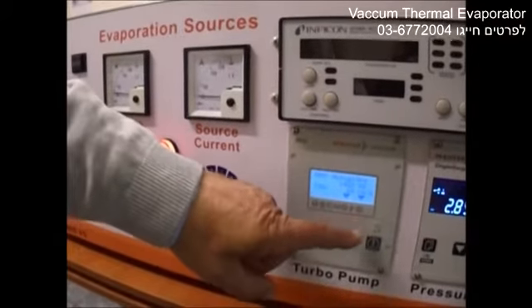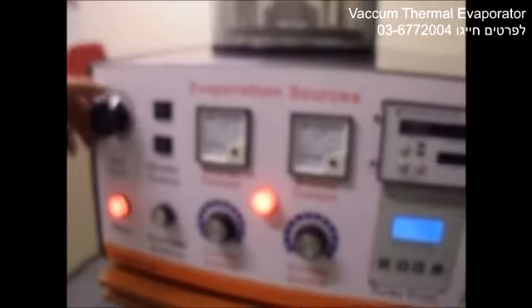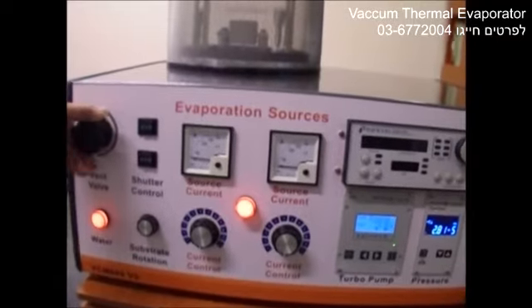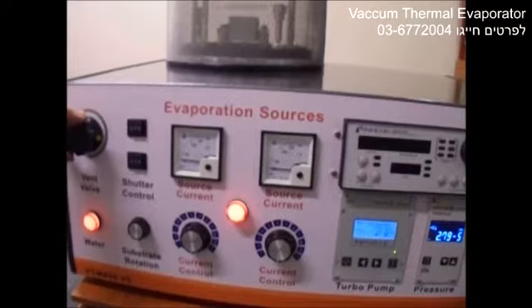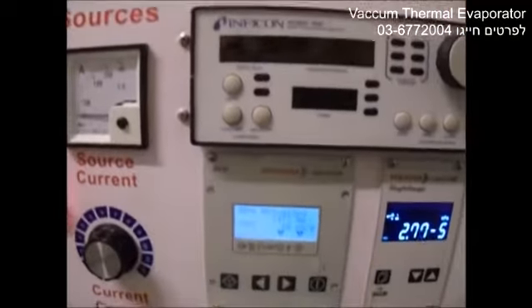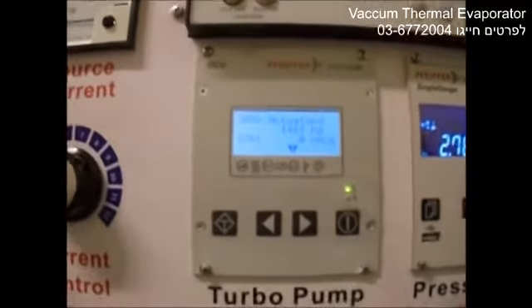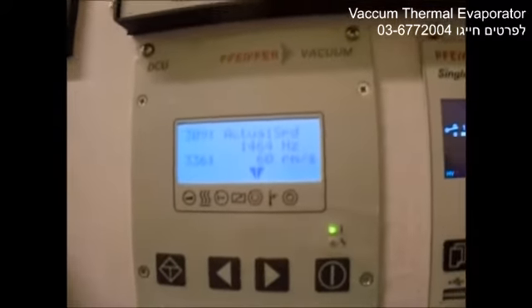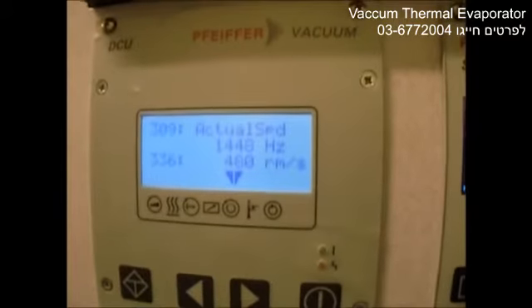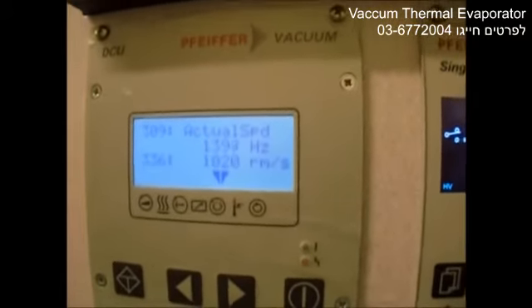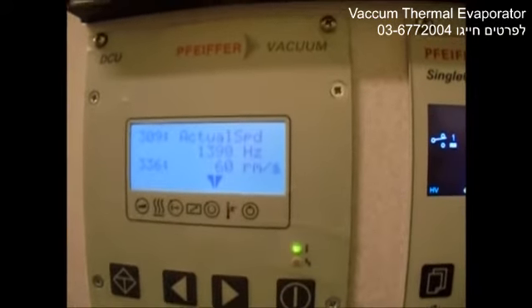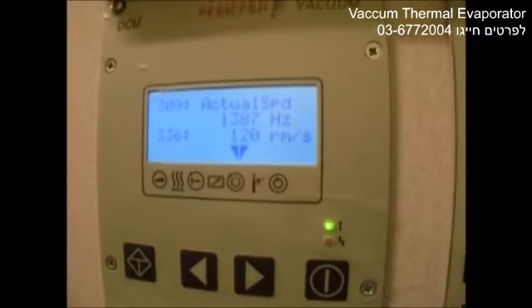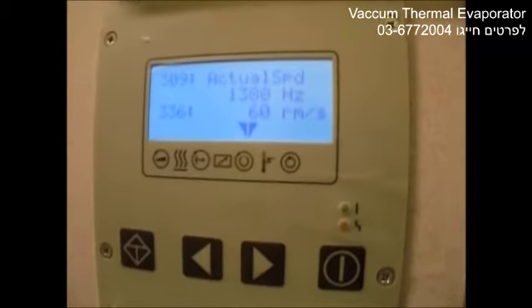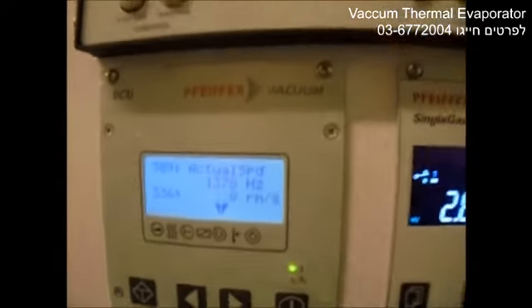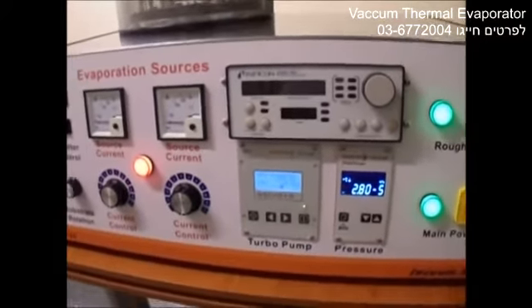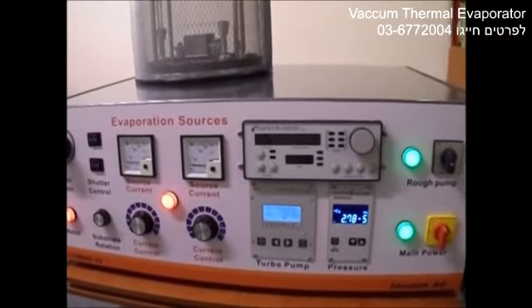We turn the turbo pump off and using the variable leak vent valve, we can start venting the system in a way that the deceleration value presented on the turbo pump controller is not more than 300. This is a big number. It's not more than 300 RPMs per second. This way we can vent the system faster. It is recommended to use dry nitrogen as the venting gas, as this protects all the environment of the vacuum chamber.